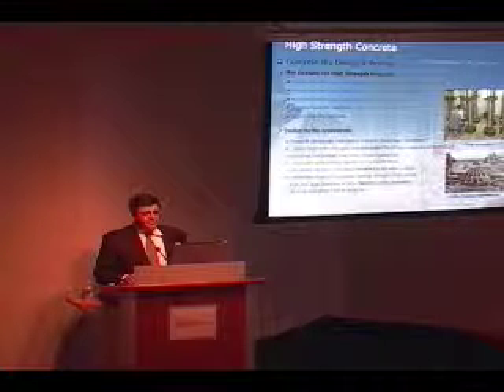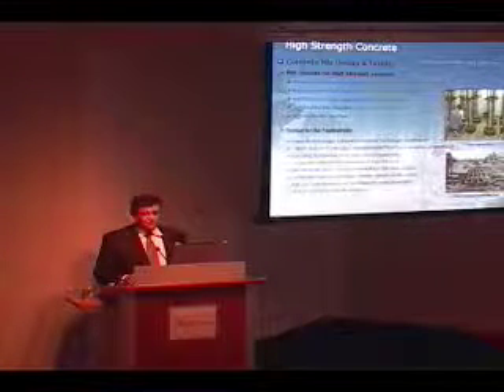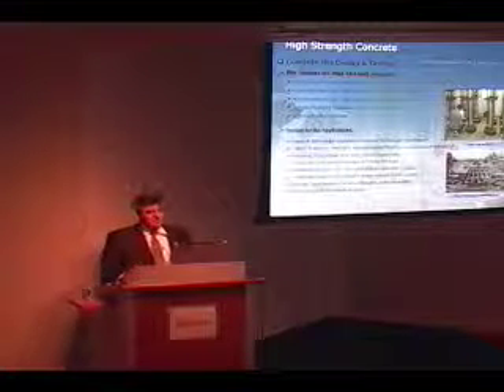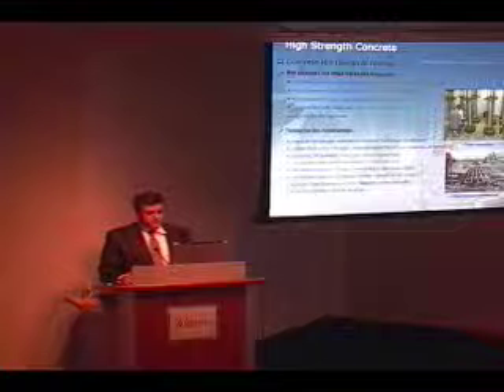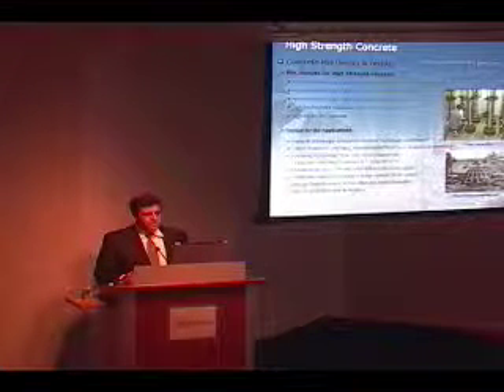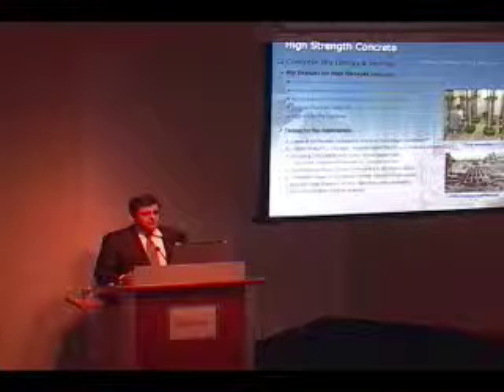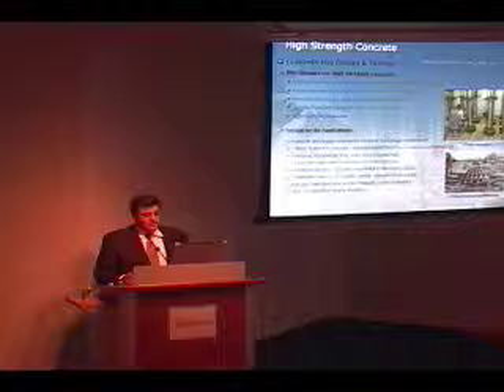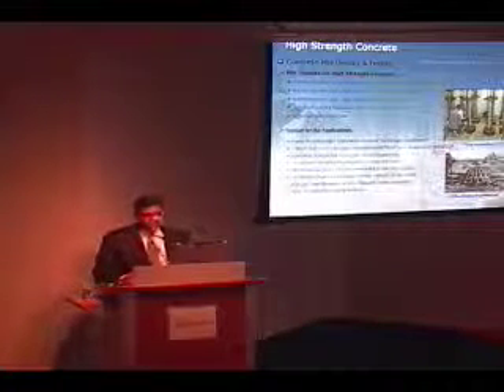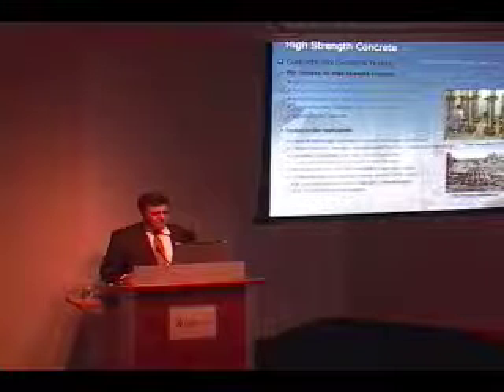So essentially we mix design for high strength. It has to satisfy the mechanical properties such as the compressive strength and modulus of elasticity. Mass concrete, anything that's very thick, could generate very high heat, and we have to be careful with the curing methods. So we wanted to create a mix that generates low heat of hydration, and also we considered high volume fly ash in some areas. Achieving a very high strength in order to achieve the 3-day cycle was also very important.